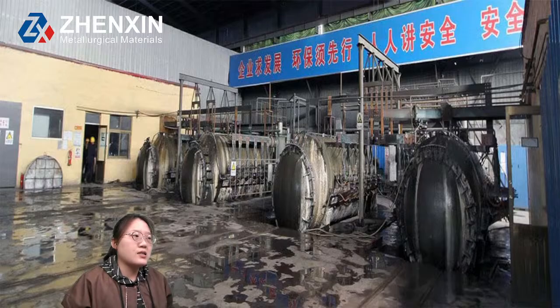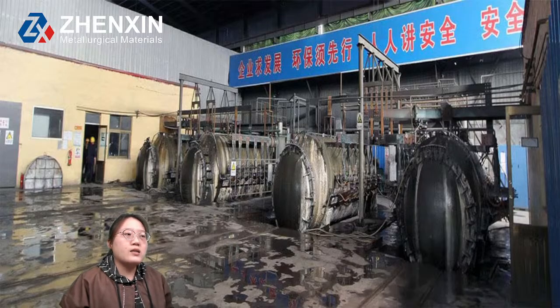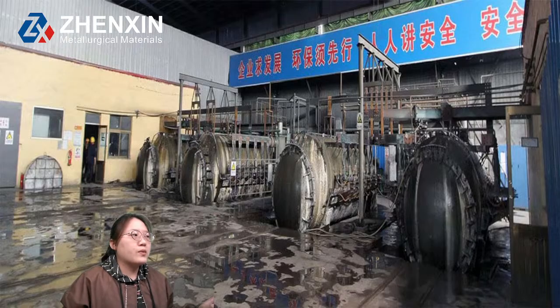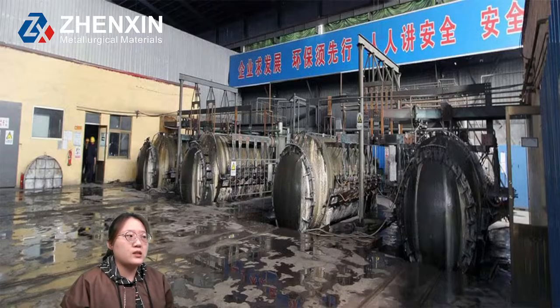It's another key material in the foundry process. Where the nodulizer decides the shape of graphite, the inoculant determines how much graphite forms and how evenly it's distributed. The inoculant is usually added after nodulization, just before pouring the molten iron into molds.